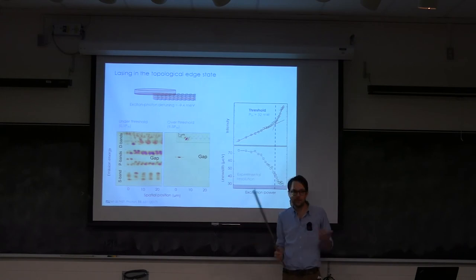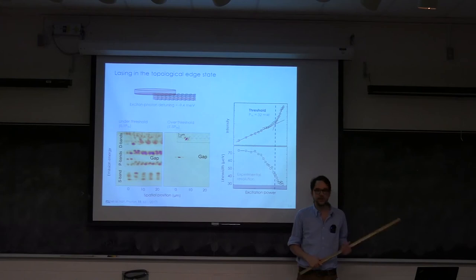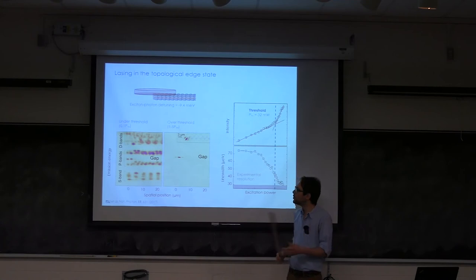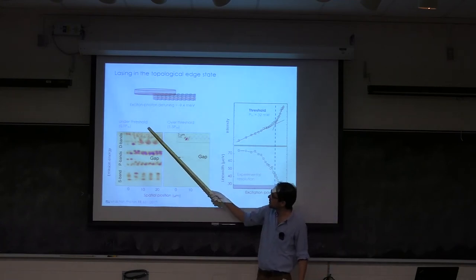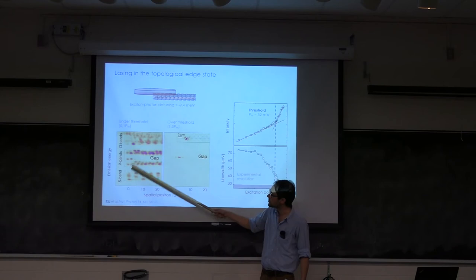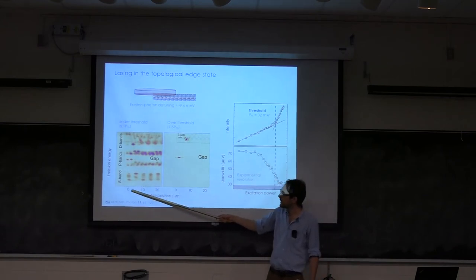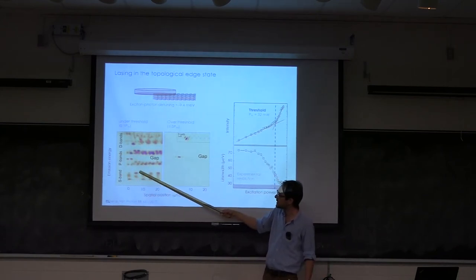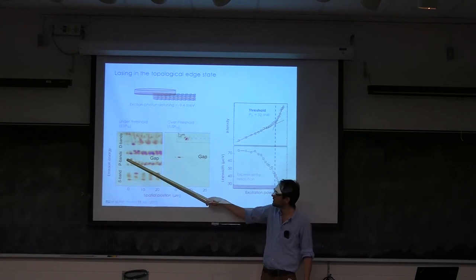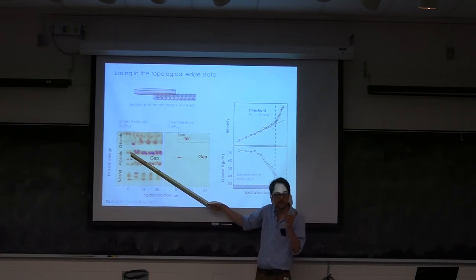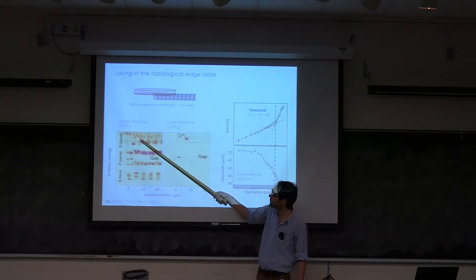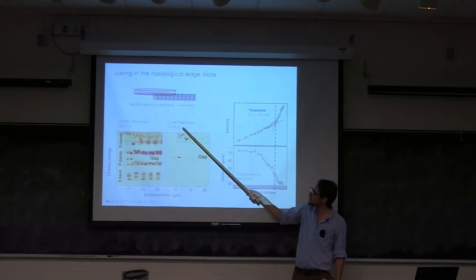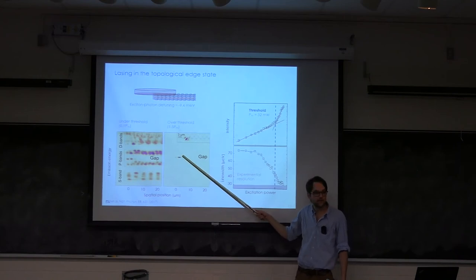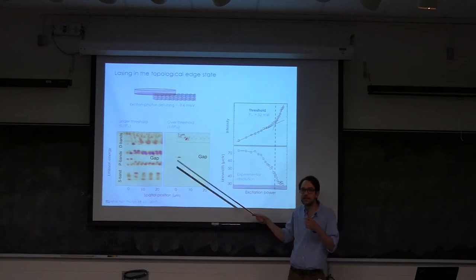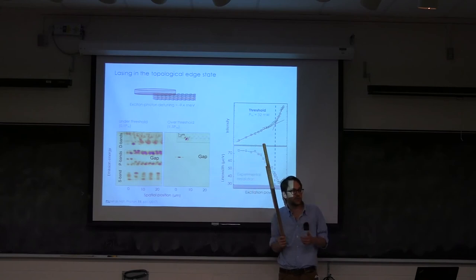And if you choose carefully your parameters, your detuning between the exciton and the photon, your pump power, your pump wavelength, you can have, in fact, this is below, at low power, below a lasing threshold. So we have, as a function of space, energy, our sets of bands. This is the S band. This is the 2p band with the edge state here. You have two lobes because these are p orbitals. And you have higher energy bands. And beyond some threshold, you see that all the intensity comes from a single edge. So this is lasing action occurring in a topologically protected edge state.